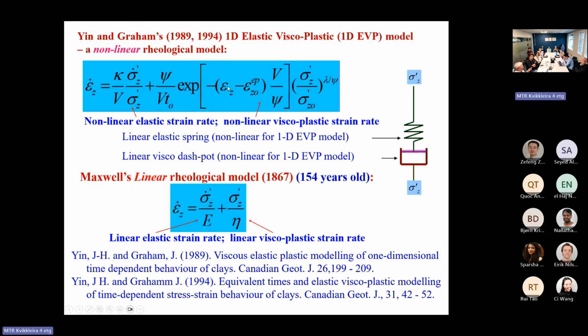Okay, for example, in a creep test on the same stress, the creep rate, the visco strain rate, is constant. But for my model, this visco strain rate depends on stress and strain. This is clearly wrong. You see, when stress is fixed, the viscoplastic strain rate is constant. It's wrong. I show you.